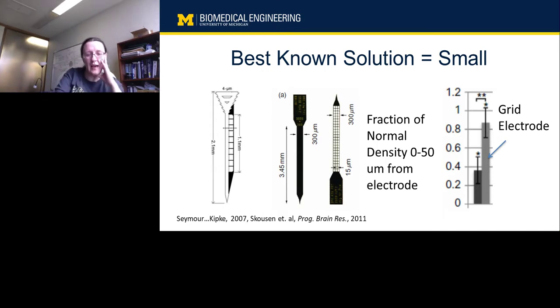So what you're looking at is two conventional silicon probes, except that they have a lattice element. What's important about that lattice element is that the individual components of that lattice are 15 microns or smaller. And at that size, it's actually smaller than a neuron.